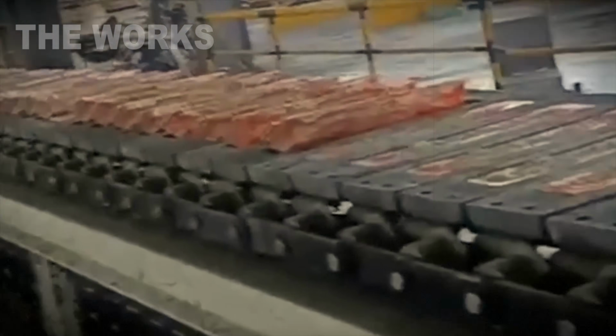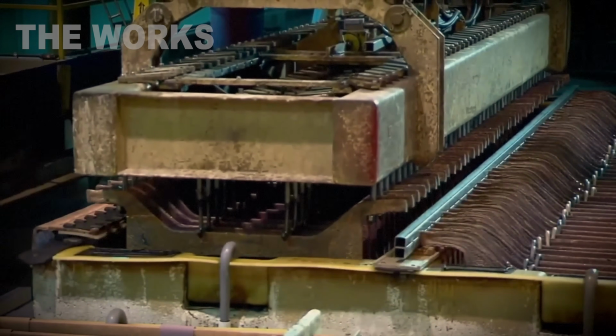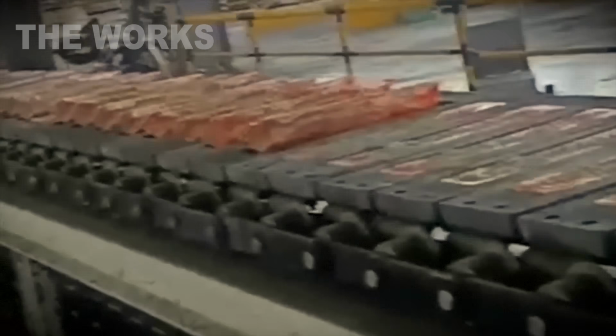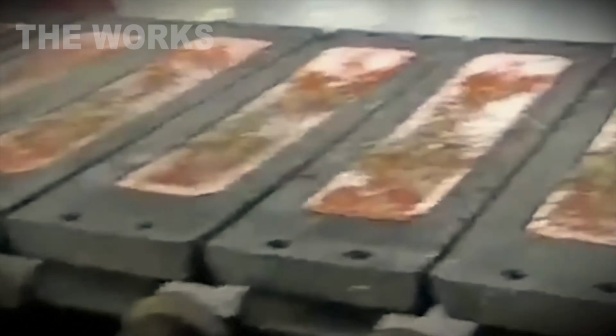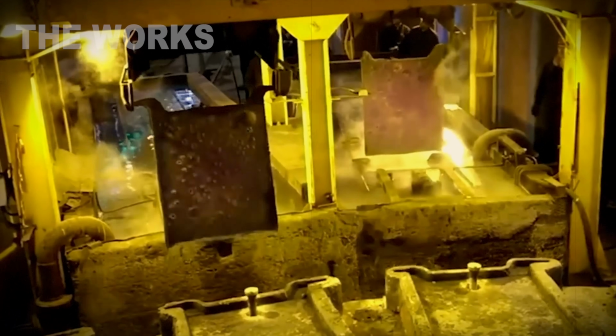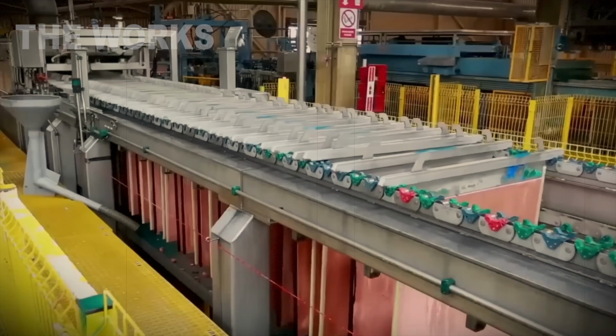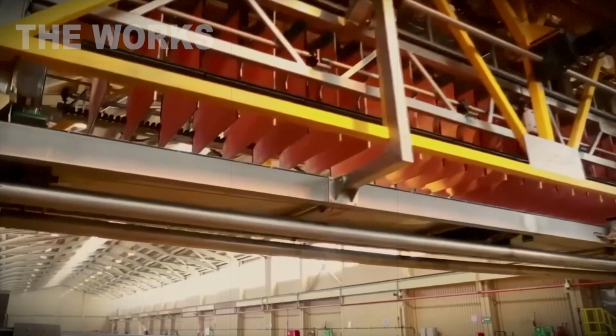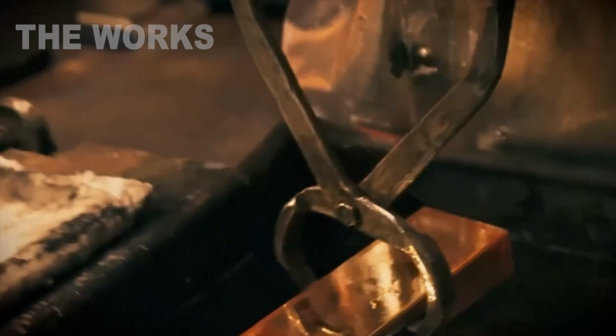A direct current runs through the solution, about 60 amps per square foot. Copper dissolves from the anode, travels through the electrolyte, and deposits onto the starter sheet. After 12 to 14 days, a cathode builds up on the sheet, a plate of pure copper weighing 130 pounds at 99.99% metal content. That's grade A, the highest category of exchange copper on the London Metal Exchange.